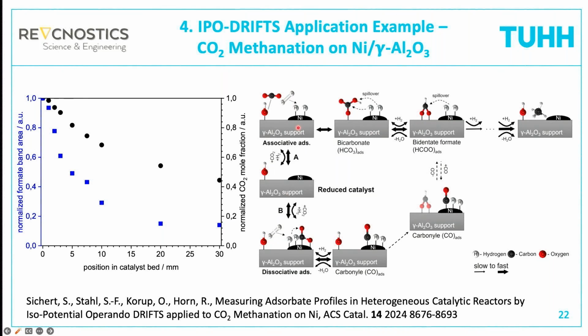We cannot see much of carbonate species, so this reduction step seems to be fast, and we also cannot detect any other oxygen species downwards of formate, so also these steps have to be fast. But the reduction of formate seems to be the rate determining step, which is why the formate builds up to a measurable concentration. All the details you can find here also in the reference that is given below.